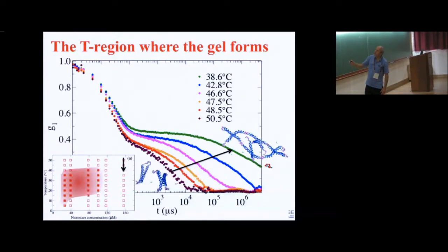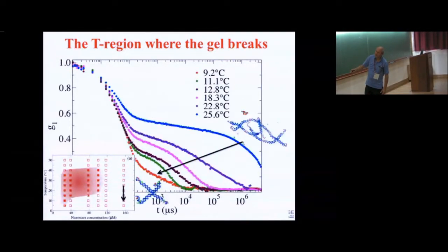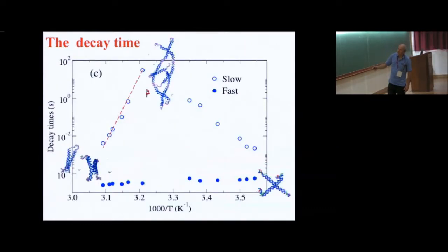So again, from 50 to 40, roughly, until you go down to 25, so much lower temperature. And then you start to see the correlation function coming back. And you see that it becomes faster and faster, and again, it has the same time scale as at high temperature. So you put together all these points: the alpha relaxation time gets slower and slower, then goes well beyond what we can measure, and then comes back, becomes faster and faster. So we really reproduce in the experiment exactly the physics that we had in the simulations, using these DNA particles.